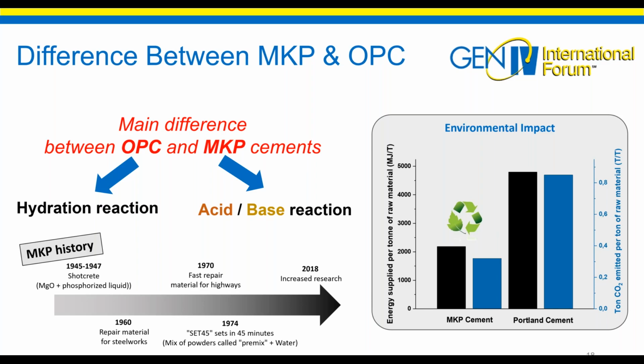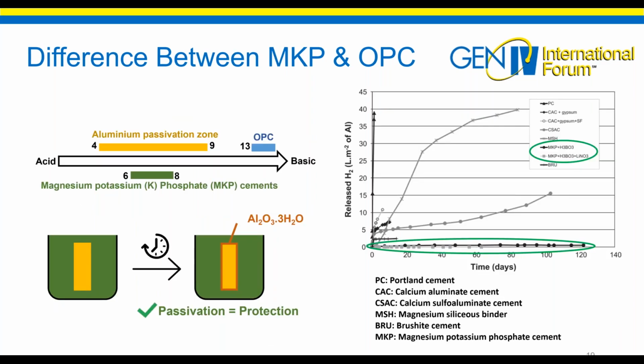The phosphate matrix was first used as shotcrete, then as a repair material. It was in the 70s that the first premixes were created. Now, research on this matrix has increased. Another notable difference is the pH of the porous solution. For Portland cement, the solution has a pH greater than 13, while for the phosphate matrix, the pH is between 6 and 8. This clearly shows an incompatibility of the Portland cement matrix with metallic aluminium.